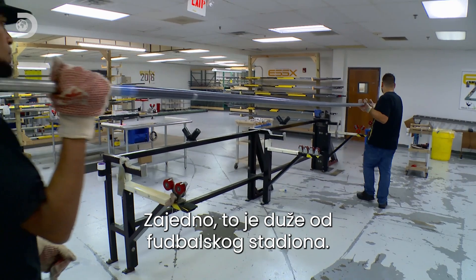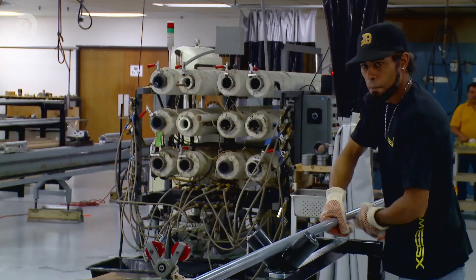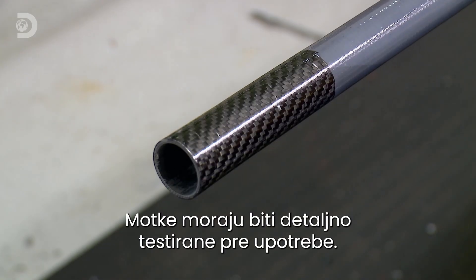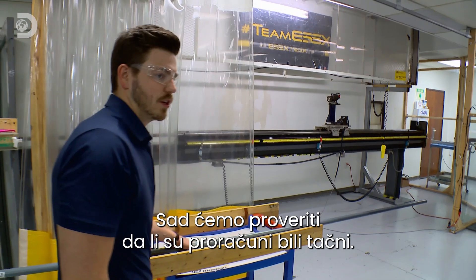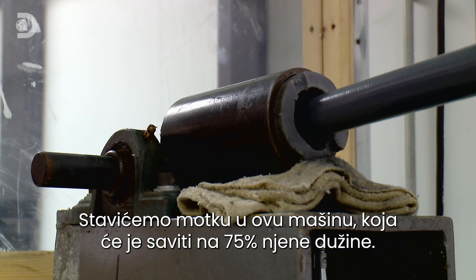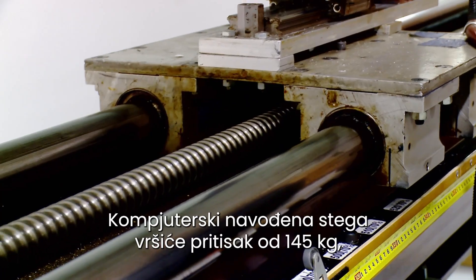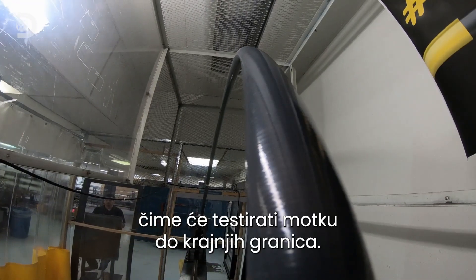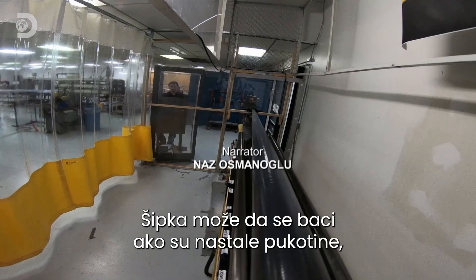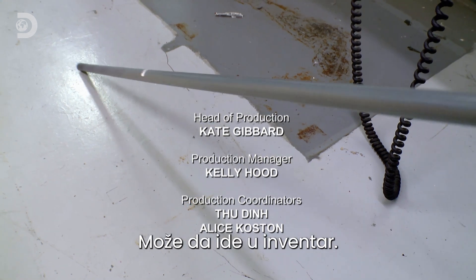The mandrels are removed before the poles cool, but top athletes can't take chances with their equipment — it has to be thoroughly tested. A computerized vice exerts up to 145 kilograms of pressure, compressing the pole to 65% of its original length to test it to its limits. Any cracks would render the pole useless, so Joseph examines it carefully. No cracking is found, and it's good to go into inventory.